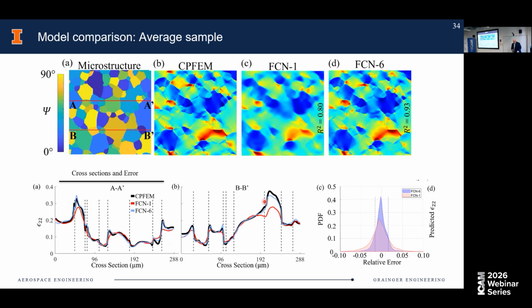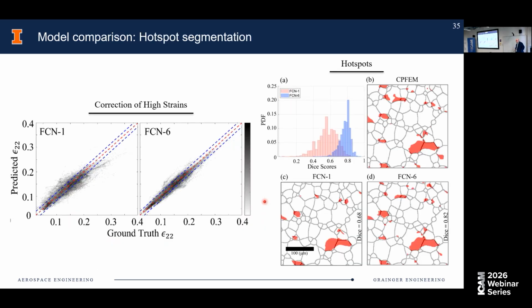And this is very important because it allows us to pick out hotspots, and you can see that here. This is what is called the Dice score. It's another image metric that we found useful. Essentially it concentrates on certain locations of the image that we consider hotspots, that's above 90% of the strain field. This is, again, the ground truth. And there's a significant improvement with these hotspots, which you can see here. This is the entire data set. This is everything, all 9,000 samples, all strain levels. And these bands are plus minus 2%.